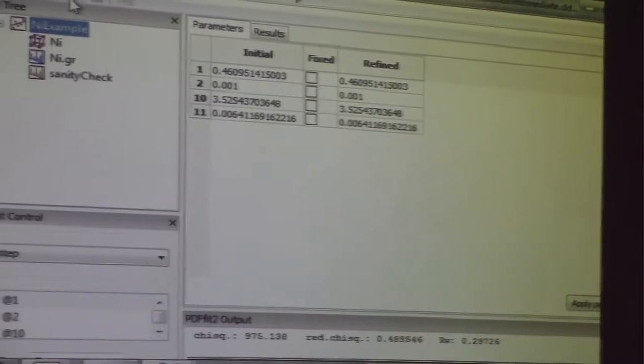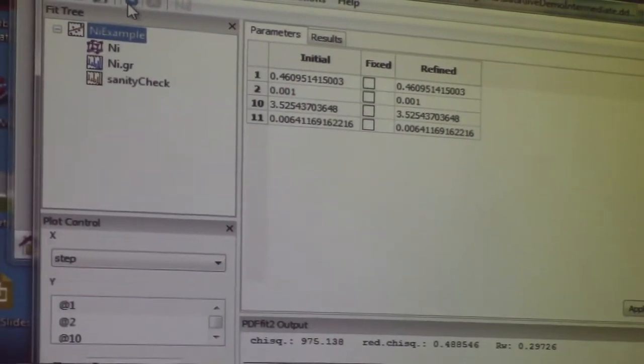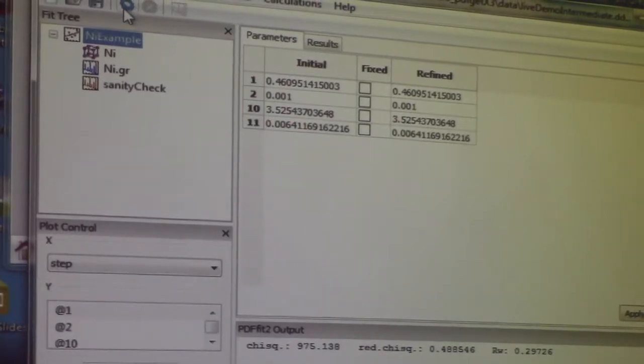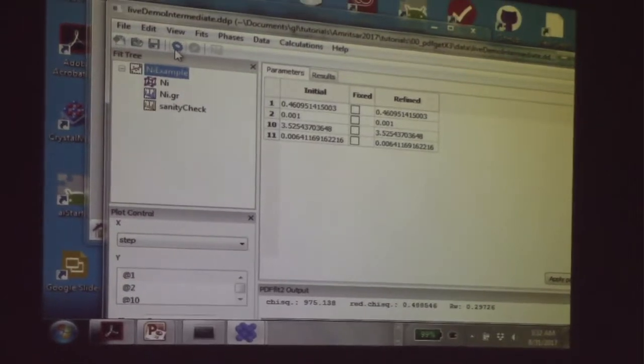So what the program did is it tried to change that value by a small amount, but because the value was too small initially, the small change was so small that it didn't produce any change, and then the program didn't know what to do. So we can actually unstick it. This is something about numerics and numerical stability. It's a mathematics thing. But we could do 0.05. So we'll set that guy to 0.05, and then we'll try again.